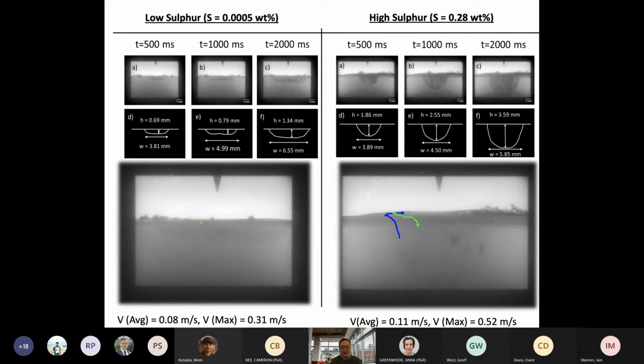So if you look at this time-resolved image, looking at 500 milliseconds, then 1000 milliseconds, then 2000 milliseconds, we analyze the shape, mainly looking at width and depth at different times to see this morphology evolution. And also you will see the average speed of these particles. The average one will be 0.08, the maximum one will be 0.31 meters per second. The average one is sometimes not very accurate because it's a 2D projection of a 3D phenomenon.